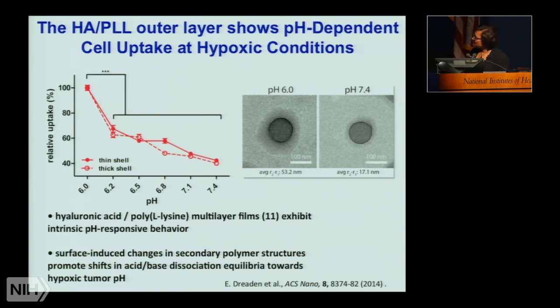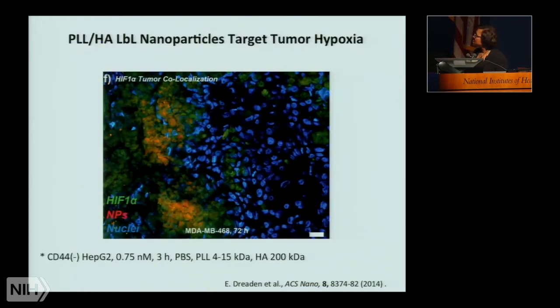So the interesting thing here is that with these two changes, we see a huge increase in cell uptake, non-specific cell uptake. This means that if we're able to enter a tumor that is hypoxic, we may be able to enhance the uptake in hypoxic tumors based solely on the physical-chemical properties of the layer-by-layer film. So we tested this, and we found that when we injected animals with solid tumors and looked at where those nanoparticles localized, they co-localized strongly with hypoxic regions of the tumor. Here we used HIF-1 alpha as a way of labeling these hypoxic regions. The nanoparticles are labeled red, and you can see this overlap in this yellow zone here.